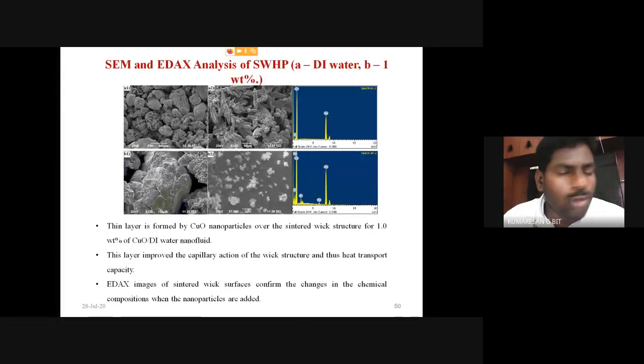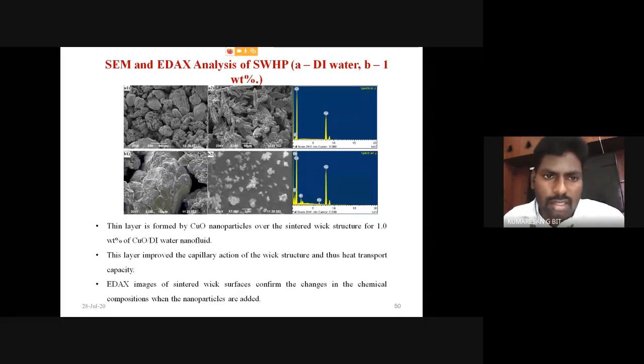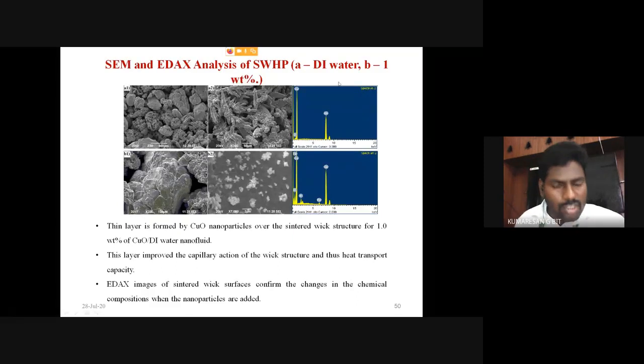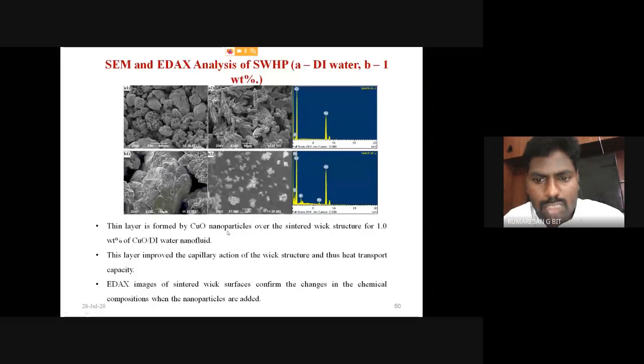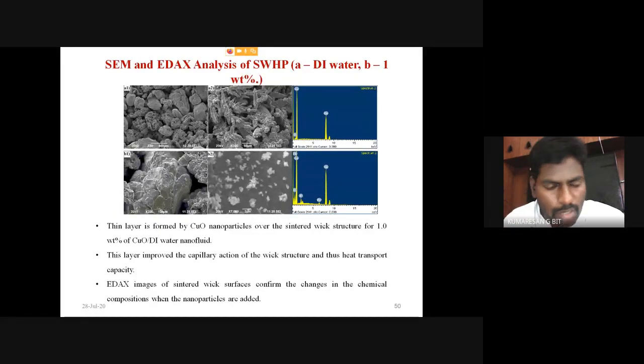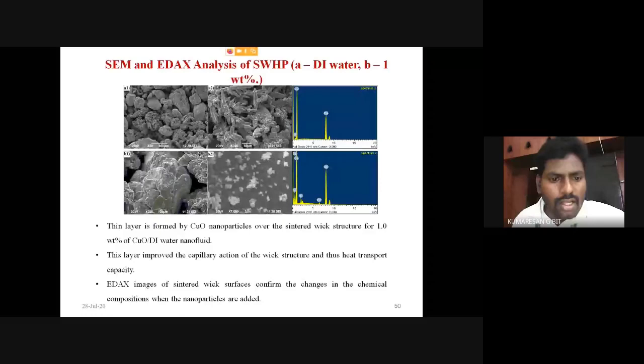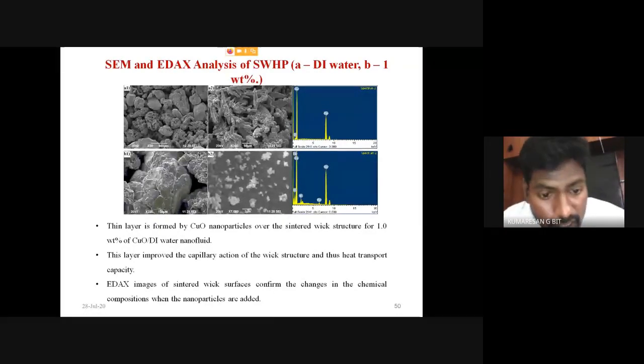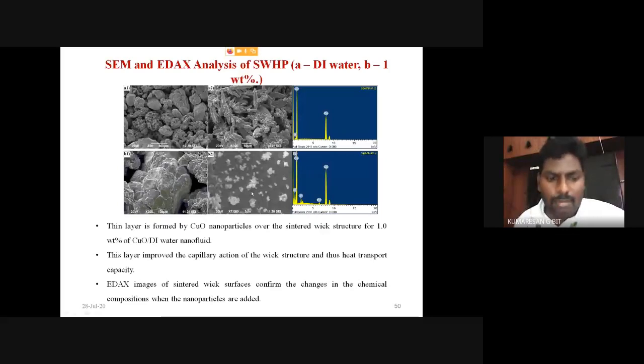After the experiments are over, the heat pipes are broken, and the wick structure present inside the heat pipes is taken for the HRTEM analysis. Then you see the thin layer. A thin layer is formed by CuO nanoparticles over the sintered wick structure for 1 weight percentage of copper oxide DI water nanofluid. The formation of this layer improved the capillary action of the wick structure and thus the heat transfer capacity of the heat pipe.